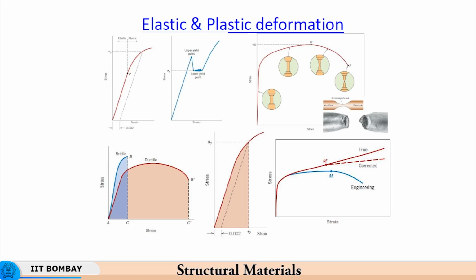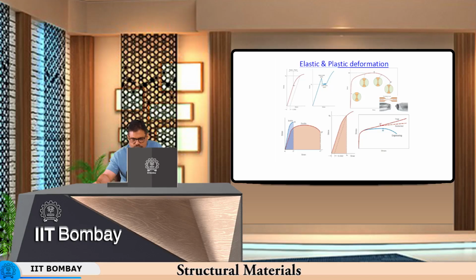Now, all steels do not cause Luder's bands. In fact, many of the steels which are used for industrial practice do not show this feature at all, but it has been shown here to educate you on the fact that this feature can appear in the material, and this has to be eliminated. Once you eliminate this, then you will eliminate the problem of Luder's bands in the components you form on the shop floor. So, ideally speaking, you should not have this, and there are ways and means.